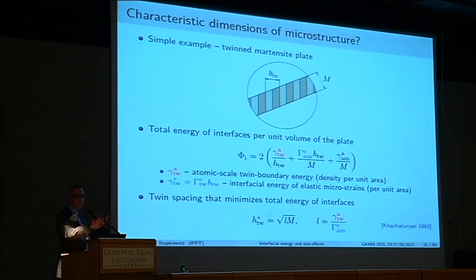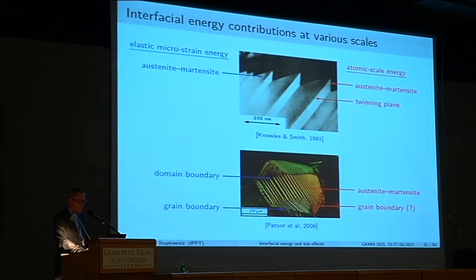So there is a competition between these two terms, and if you do minimize with respect to H, you get this kind of classical scaling law, where the spacing of the twins is equal to the square root of the thickness of the interface, and small l is a characteristic length introduced by these two quantities in red and in blue in this picture. So this is a classical result, but we will see that it also holds in more complex situations.